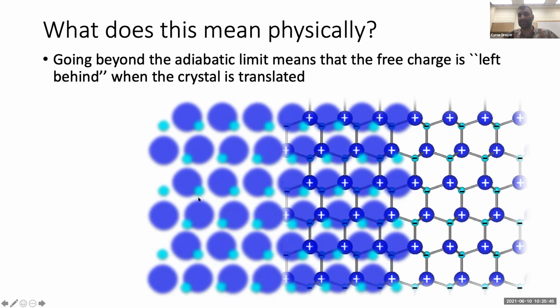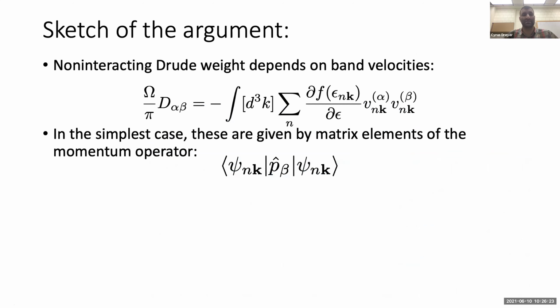And this charge density that is left behind by the atomic displacement is exactly the free charge in the material, the free charge in the metal that's not tightly bound to the ions. And that free charge is given by the Drude weight. So we get an extra current that is given by the fact that the free charge is left behind, and the free charge is defined by the Drude weight. Okay, so that's a physical picture of this result. So I'll just again give a sketch of the argument as to why this is the case.